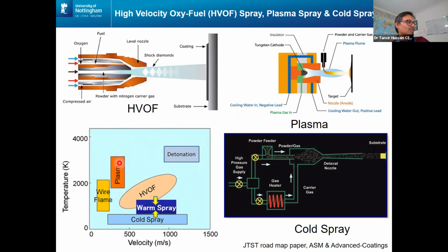Plasma is incredibly hot as a system. And here we're talking about 10,000 degrees Celsius, so similar to the surface of the sun. In a plasma spray, you have a tungsten cathode and a copper anode, and we are injecting a plasma gas. And within that plasma, we are then injecting a powder, and that powder particle is melted. That's then accelerating and hitting the substrate to form a coating.